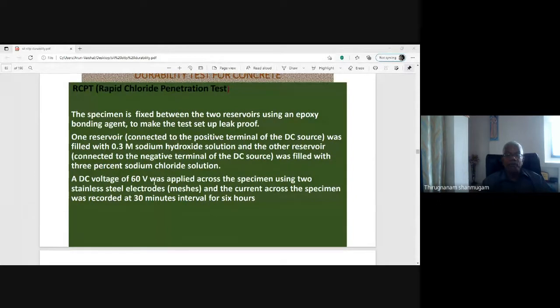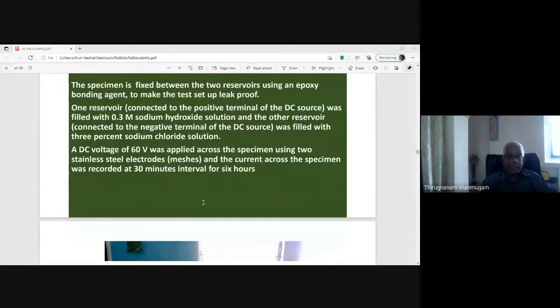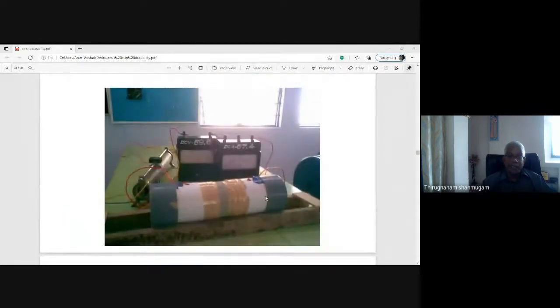A DC voltage of 60 volt was applied across the specimen using two stainless steel electrodes, and the current across the specimen was recorded at 30 minute intervals for 6 hours. This is the apparatus, that is the reservoir. One reservoir is filled with sodium hydroxide solution and another reservoir is filled with sodium chloride solution, and in between these two cylinders, the concrete specimen takes its place with an epoxy joint to make it leak proof, and for extra leak proofing, some adhesive tapes are provided.